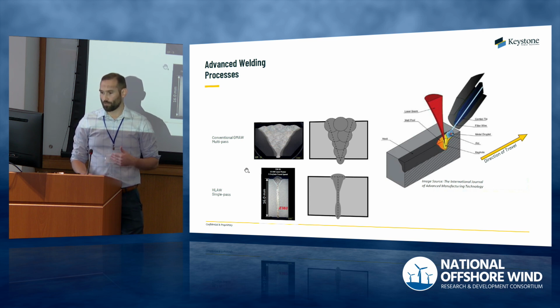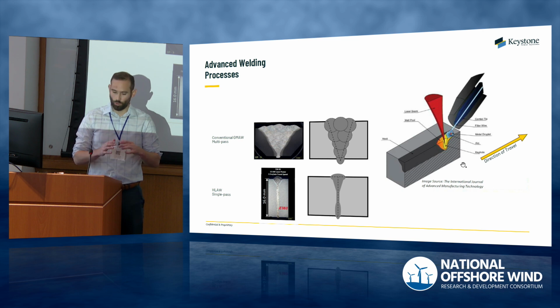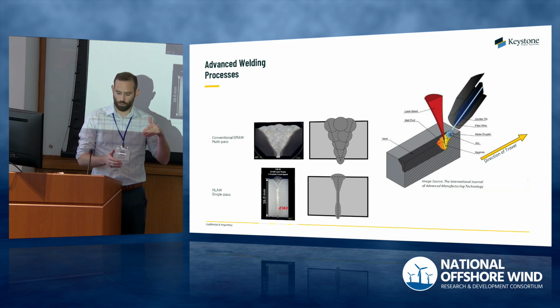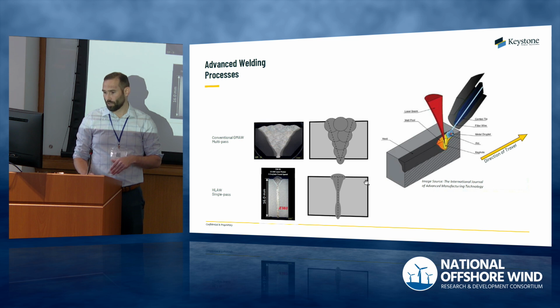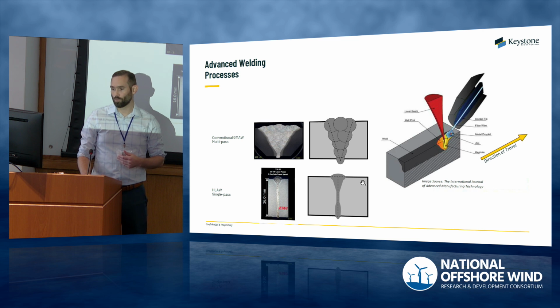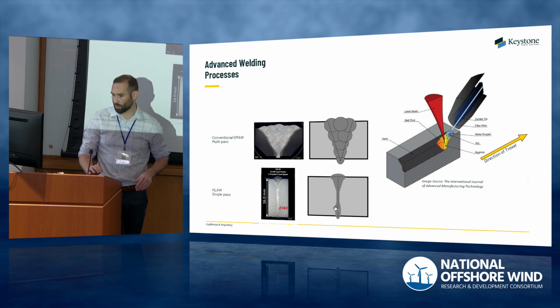Instead of having multiple weld passes, you have a molten pool of weld bead, and you shoot that into the joint using the force of a laser. So you have a much different weld geometry. This is showing a conventional V joint for multi-pass welding, as opposed to a hybrid laser arc, where you're going to have a more rectangular joint, basically just flat pieces welded together.